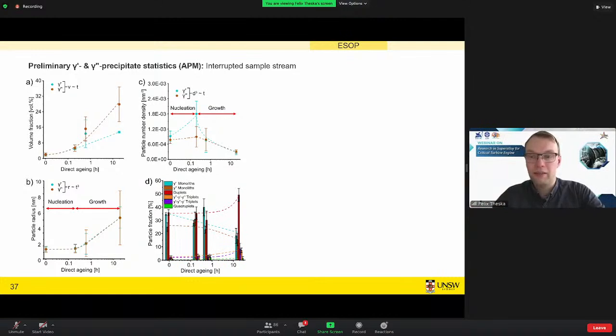Then you had a question about the low fraction of niobium. If you look at the composition of the gamma double prime, it's Ni3Nb, which is three quarters nickel, so you don't need that much niobium in there. If you remove it completely, you have a different alloy, right? You wouldn't get the delta phase, you wouldn't get the gamma double prime, of course. You might get different phases though. If you change the equilibria, that can have a large impact. I think the alloy 718 Plus was an approach to make a variant without gamma double prime, but I'm not sure how far research has come on this. There have been a couple of publications a few years ago.